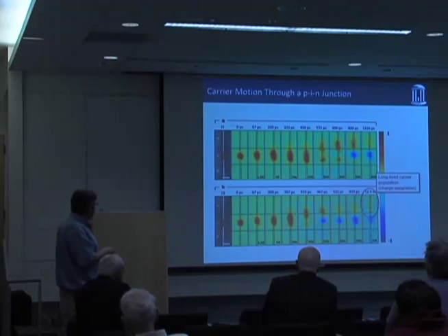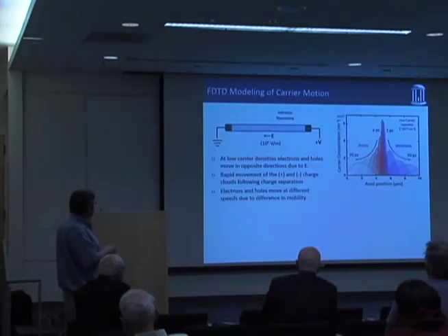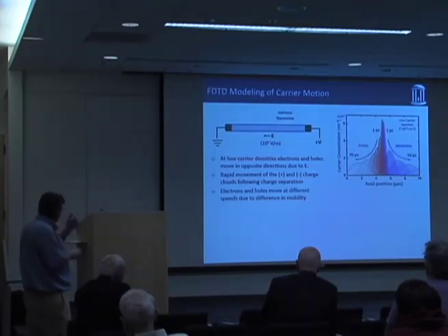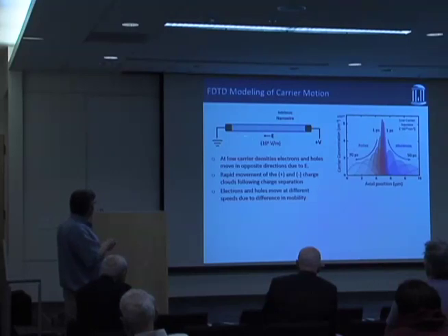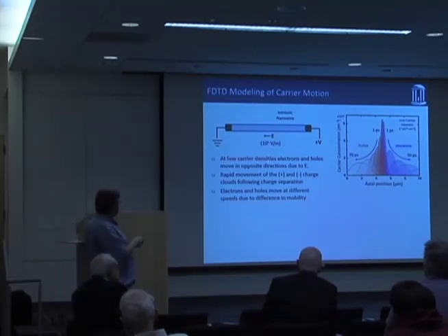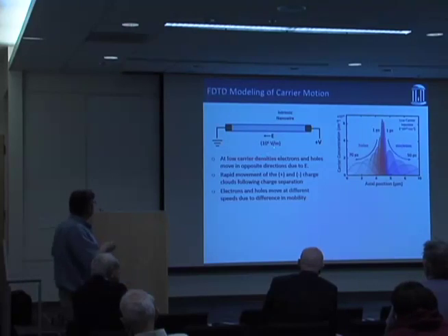And so we started to think about, okay, why is that? And so we've done these finite element modeling of these systems. And we modeled our system as just sort of an intrinsic. We just took an undoped nanowire, and we applied a bias to it so that we don't have any electrodes in our experiment. But that's how we're going to get this sort of static field. And then in the center of the wire, we create a bunch of electron-hole pairs.